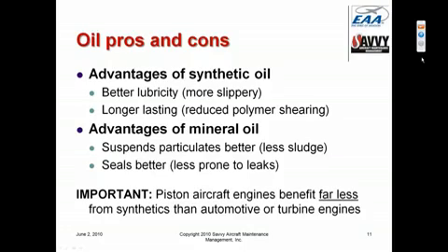The important thing to understand is that while the benefits of synthetic oil are very, very significant in clean running engines like automotive engines and turbine aircraft engines, we really can't take much advantage of them with piston aircraft engines that are running on leaded avgas. We can't take advantage of the extended oil change intervals because our piston aircraft engines are so filthy and they put so much junk in the oil that even though the synthetic oil holds its viscosity just fine, we have to drain it on a regular basis just to get the junk out. That is not a problem that we have with automotive engines, or very much, and almost at all with turbine engines, which keep their oil very clean because they don't have this big dirty blow-by problem that we have in our piston aircraft engines.